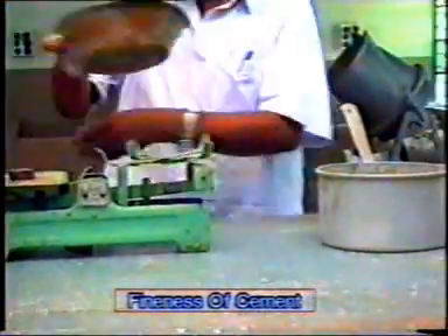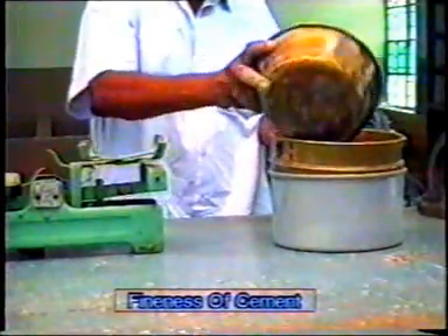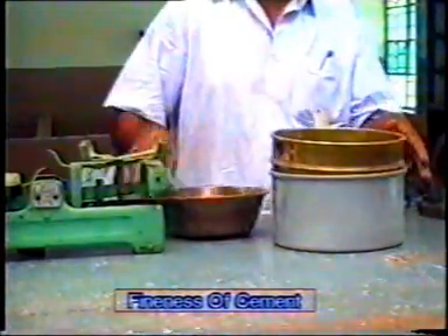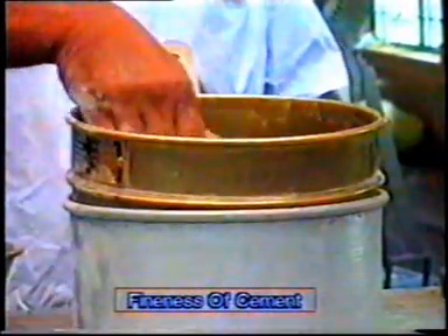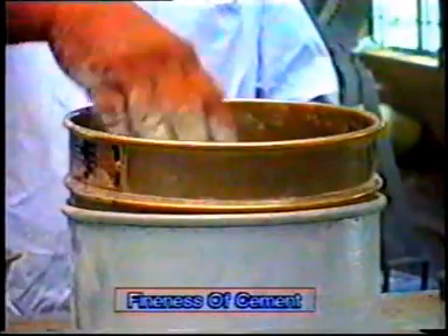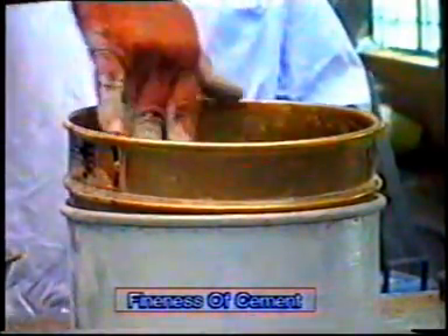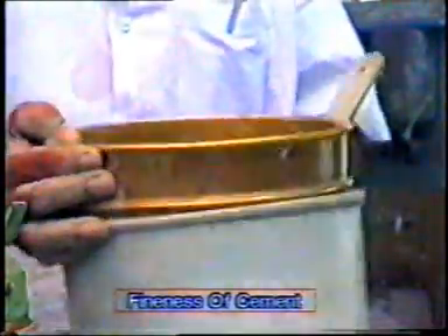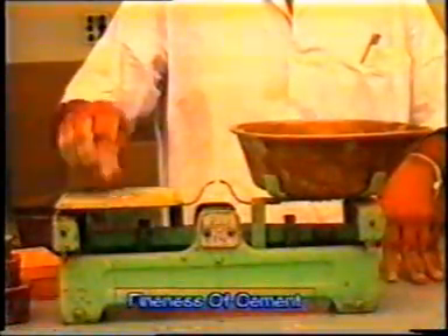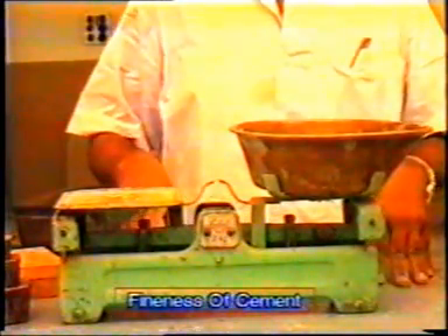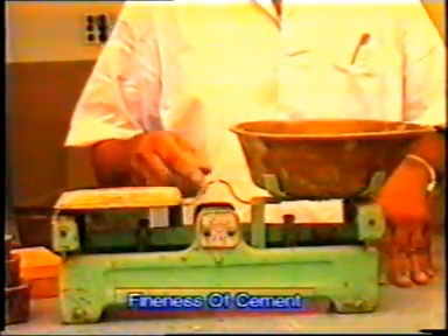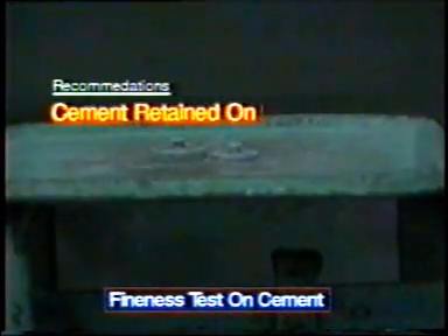Take 100 grams of cement into a 90 micron IS sieve. Break down air set lumps, if present, with the fingers. Sieve the sample for about 15 minutes. Weigh the residue left in the 90 micron sieve. Now the weight of the residue left in the 90 micron sieve is expressed as a percentage of the original weight